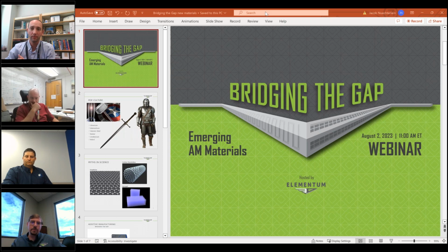I don't want to get too far into the Elementum products in this setting, but because of the formation in situ of the ceramic particles, that is one of the advantages of that dispersion mechanism - the formation of the ceramic particles in situ. But I found that the nanoparticulates, such as what GRX-810 is doing, because of the steric attachment of the nanoparticles onto the larger particles, it is quite stable.